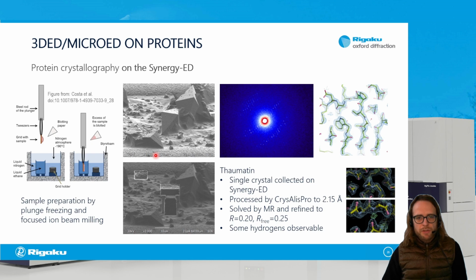We see some hydrogens in the map, and this really has only been our first attempt at it. Of course, in the research community, there are much more spectacular systems being studied than that, but we have a successful proof of principle that proteins work very, very nicely in the Synergy-ED. And this is one case where I would specifically like to highlight, again, this virtually settable detector distance, because, of course, with proteins, you have these long unit cells. In this case, it's 150 angstroms.